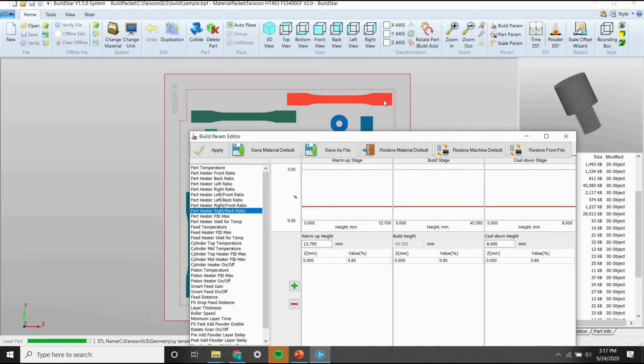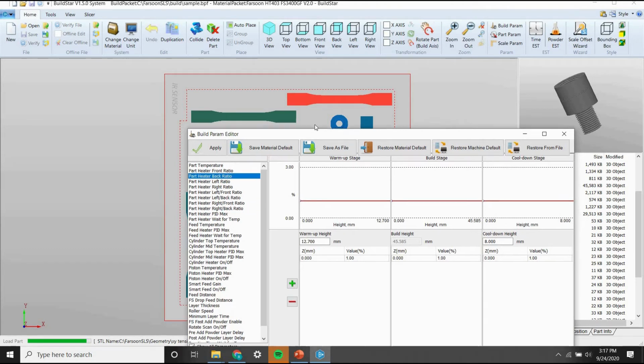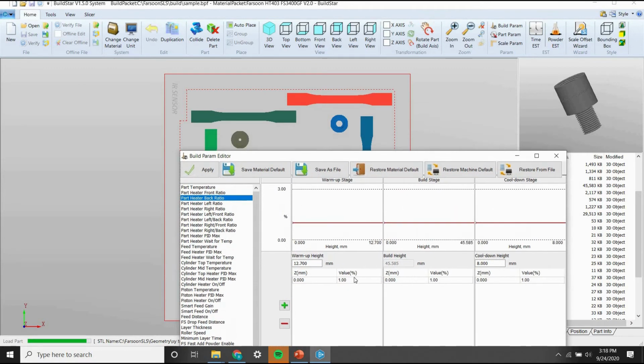So if you see that you're only getting curling, say in this very corner of the build envelope, then you're going to want to change this right back ratio. If you see that there's curling more in this middle back area, then you would change the back ratio. Usually when I'm changing heater ratios, I'll do it 0.25% at a time. This is usually around 2 to 5% duty cycle.